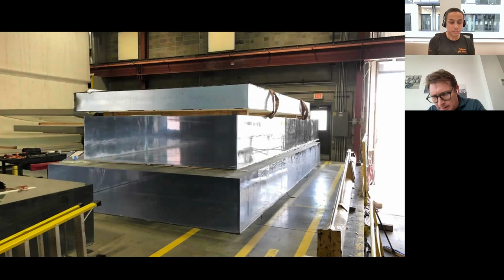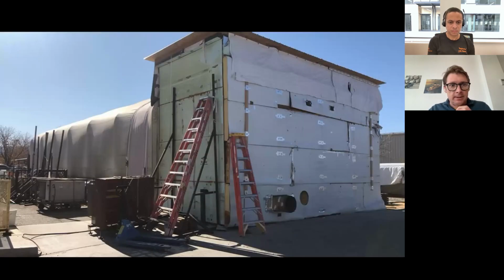This panel in the picture is about 8 meters long, but you can see from its level of clarity, it's absolutely amazing. And you would not get this with glass. Because of the size of it, they had to build an external oven to heat up and cool down the acrylic during the bonding process.